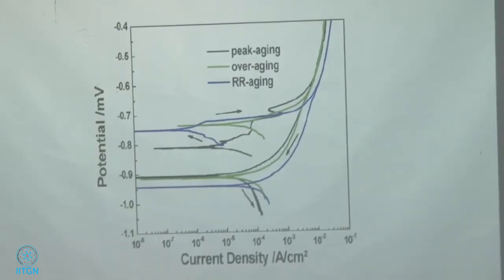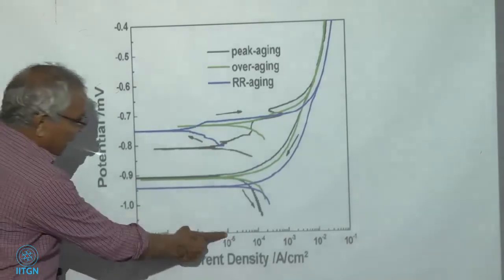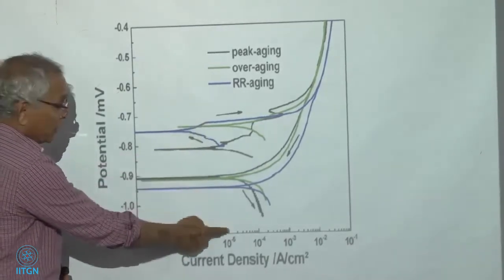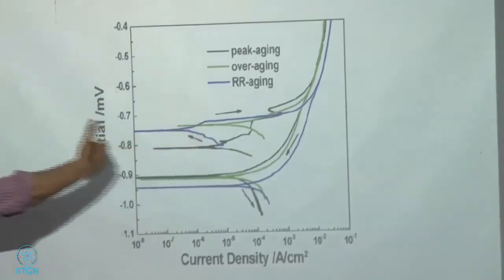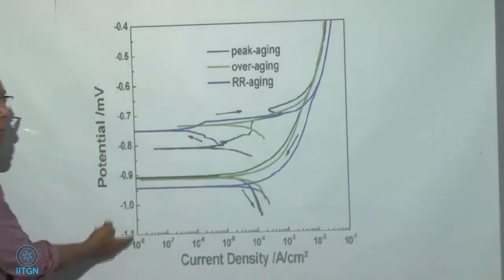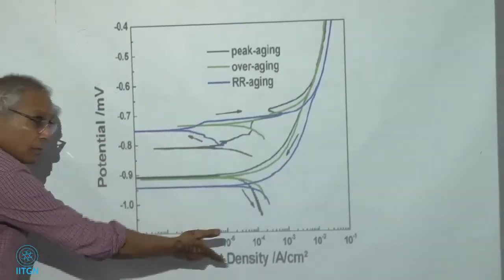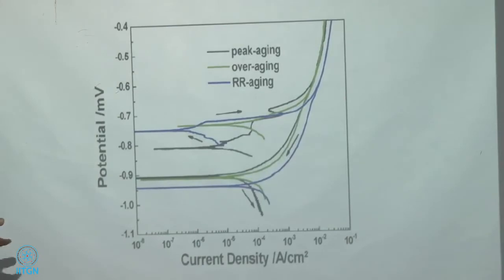So if you have a bad alloy that's corroding, it will have a high corrosion, 10 to the minus 5. If it's getting better in corrosion, it may be like 10 to the minus 8 or something. 3 orders of lower magnitude current density. Okay? So lower current density, better the corrosion.